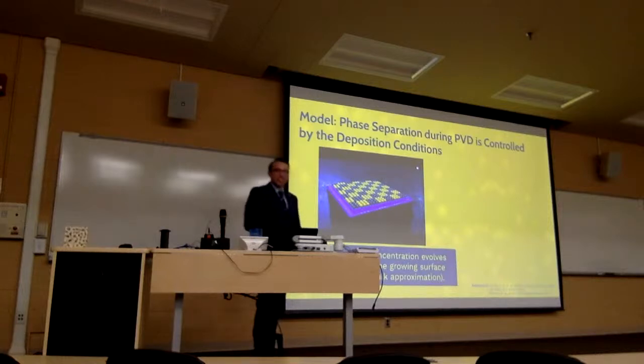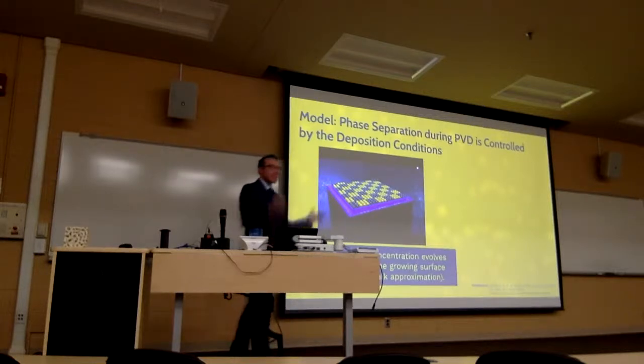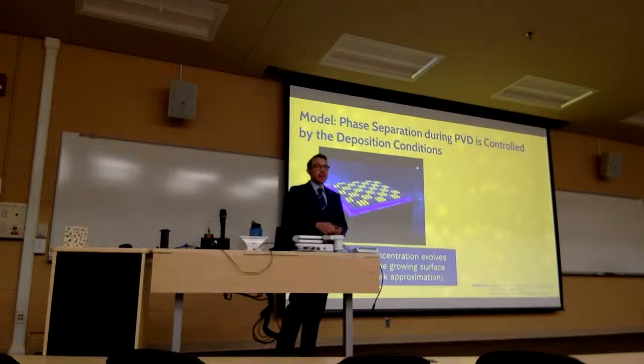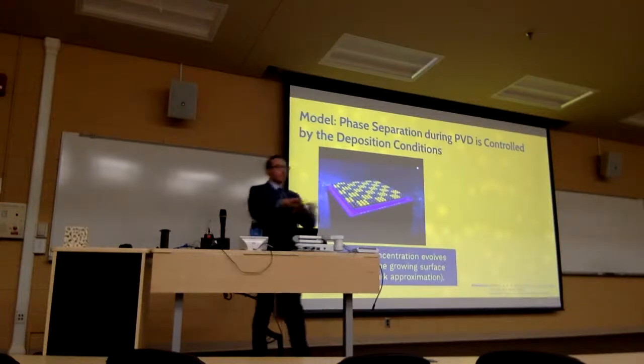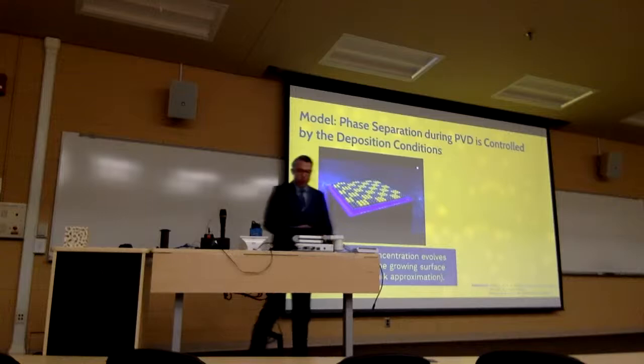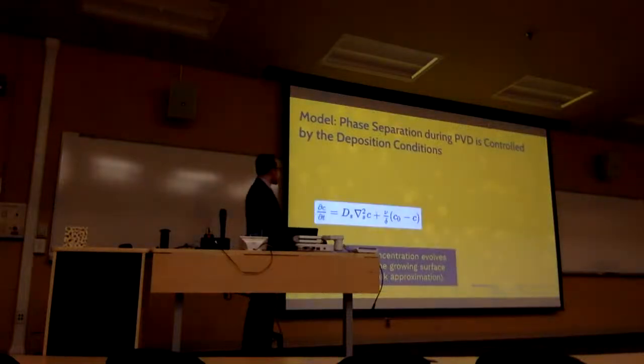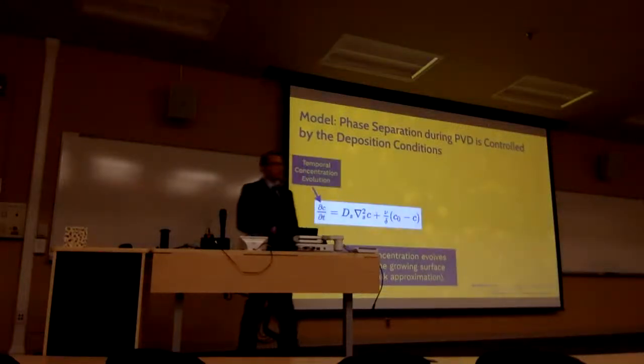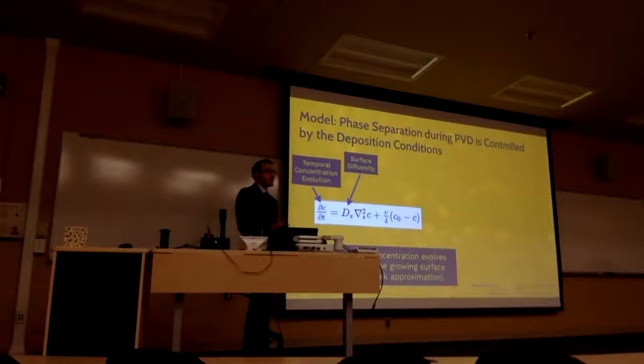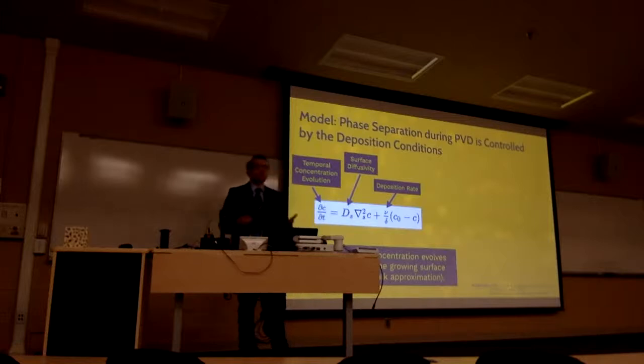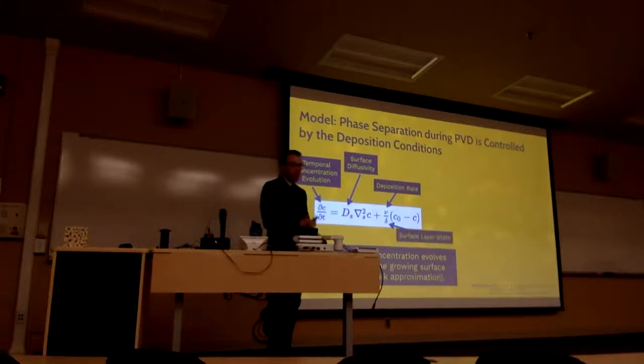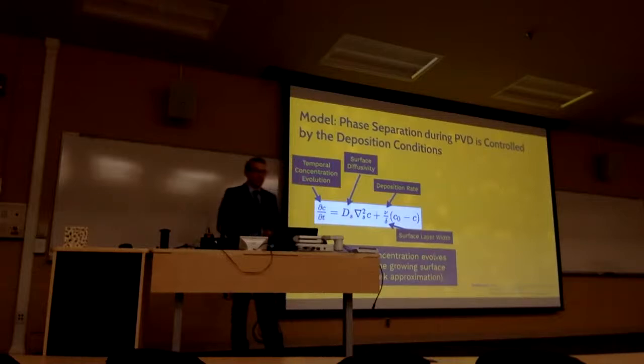So hopefully, this actually is a video that describes the phase separation process onto a substrate. What this video would actually show you is that the atoms that deposit onto the substrate actually diffuse along the concentration evolution over the course of the deposition. And so what they used was a Cahn-Hilliard formulation to describe this process, where they mapped out the concentration evolution over time as a function of the deposition conditions, namely the surface diffusivity, so how fast these atoms are traveling on the surface, the deposition rate, how fast we're adding material to the growing film, and the surface layer width, so how large is that layer that's actually evolving in concentration.